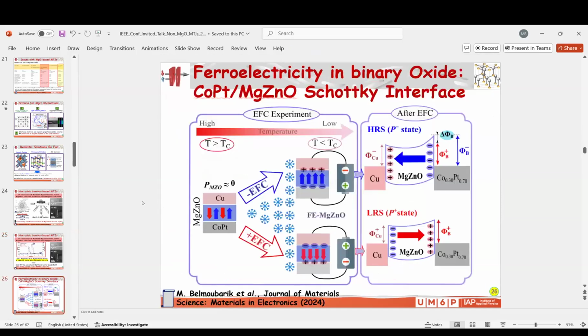So while doing my experiments, we started to find some hysteresis in the IV curves, and that was an indication of ferroelectricity. At that time, a few papers talked about ferroelectricity in magnesium zinc oxide. So implementing a ferroelectric barrier in MTJs will bring new features or options, for example, multi-bit MTJs. So we did something innovative here.